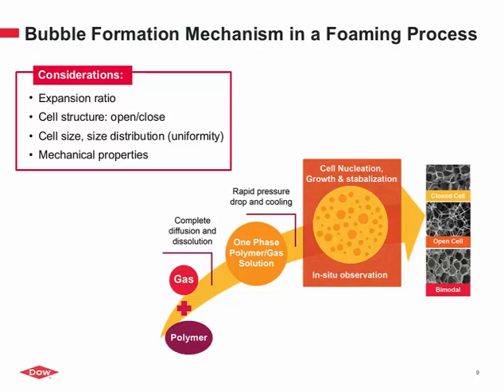Just to recap on what happens mechanism-wise in this foaming process. I already described the evolution of the melt plus gas, the formation of this polymer-gas solution, and then with the exit, the rapid depressurization and cooling, and of course the presence of the nucleating agents, we enable the bubble growth and stabilization via the cooling process itself. We can get a closed cell structure, an open cell structure, or a bimodal or multimodal structure. And of course, this is controlled by the rheology of the system that is put into the extruder.